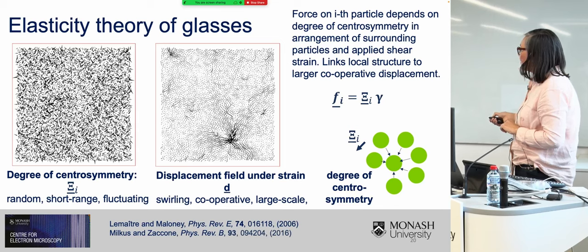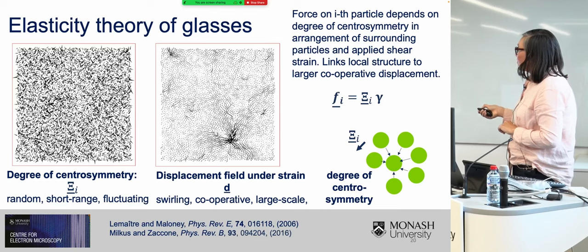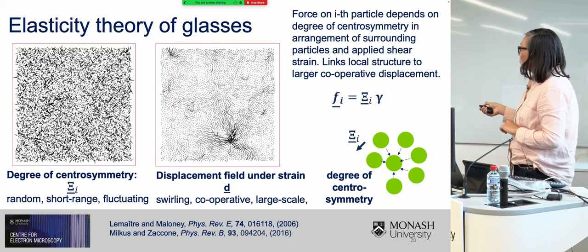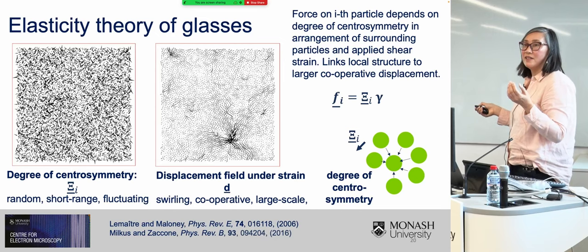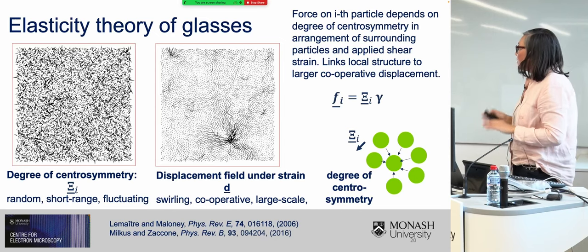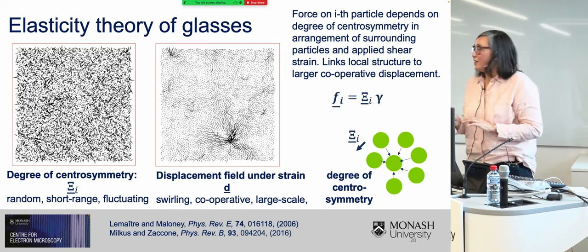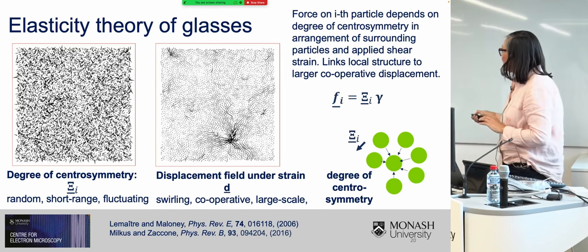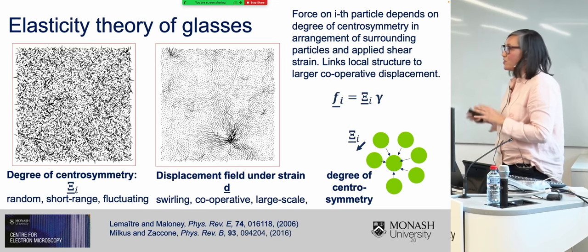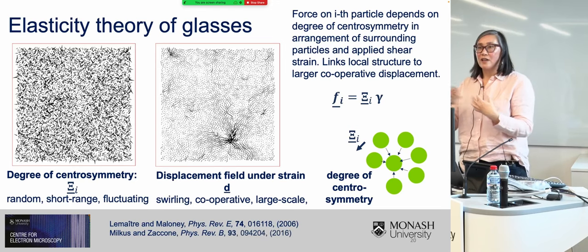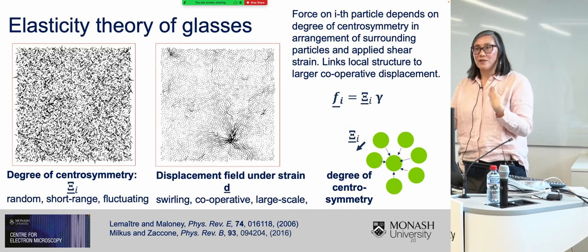And this xi i is essentially the weighted sum of the unit vectors from the central particle to all the neighboring particles surrounding it. So when we strain an amorphous specimen, the force imbalance on any given particle is actually equal to this vector parameter, the degree of centrosymmetry, multiplied by the applied strain. And the reason why this is a very interesting idea is because it takes this really local information and strongly links it to the larger scale cooperative motion that you see when you strain the material.